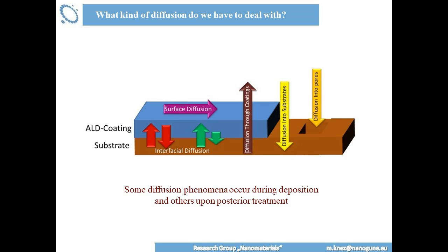So now, what kind of diffusion processes can happen during or after the ALD process? I mean, you are preparing samples, you are coating your substrates, and you don't, in many cases, want to use them just as they are. So you are making samples for a certain purpose. So you don't only have to account for diffusion phenomena during the ALD process, but also in certain post-treatment conditions. It doesn't help you if you have a perfect coating before your post-treatment. If you need to treat your sample in order to have a functionality, and during this post-treatment you again have something else which destroys the sample or makes it different than it should be.